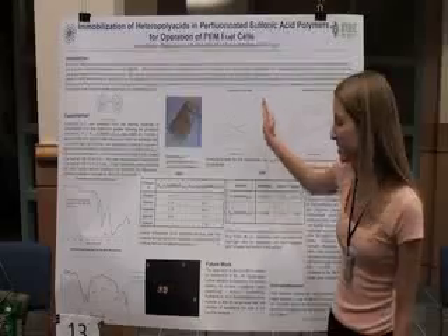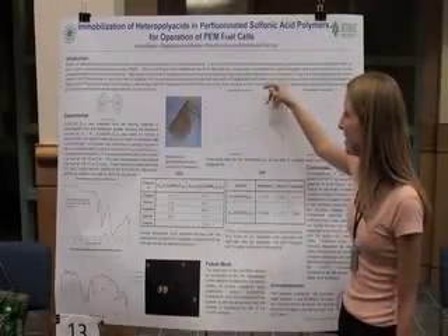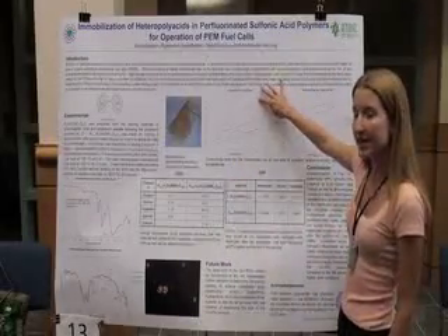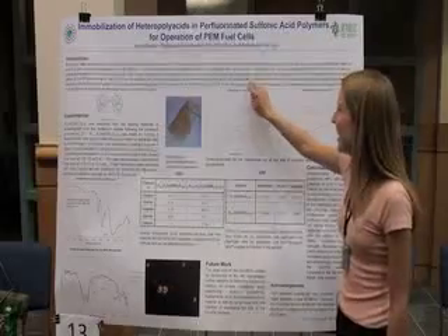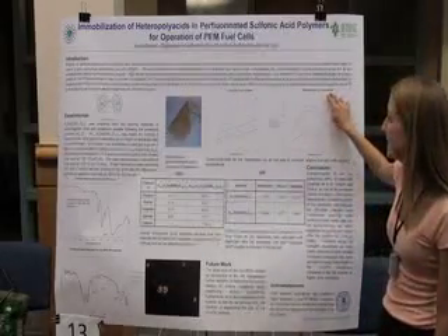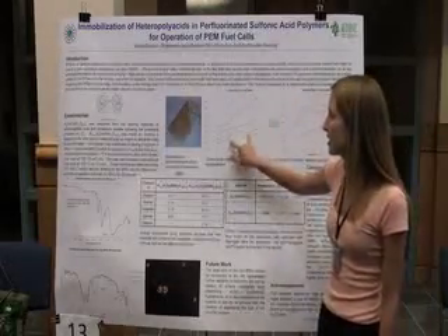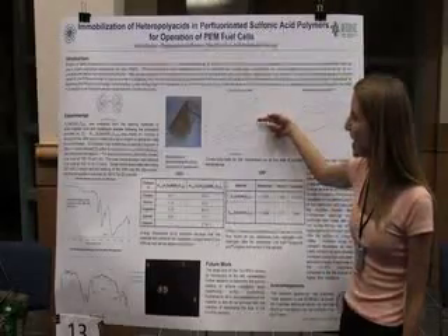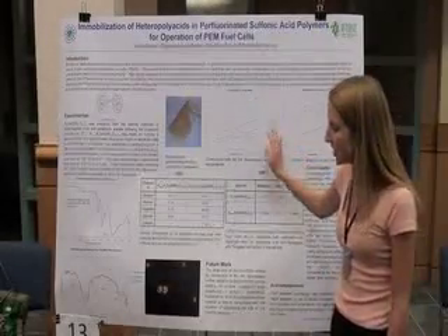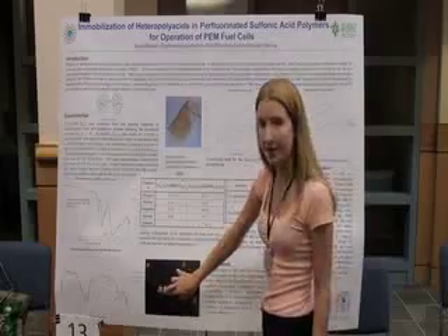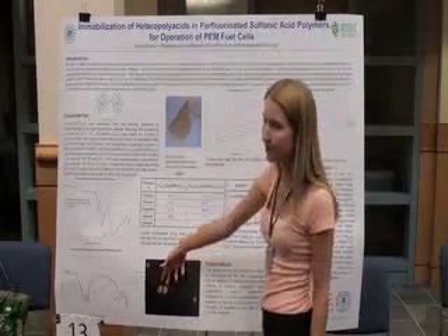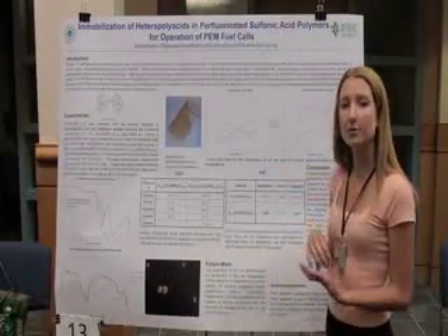So this is going to take us into the further work because, as you can see, the loading at 0.5% has a much higher conductivity at these relative humidities than does the 3M ionomer, but as you add more of your HPA, it actually decreases. That's because the HPA tend to agglomerate, and they're very large, on the order of micrometers here. So they're taking up volume that could otherwise be used to transport protons.